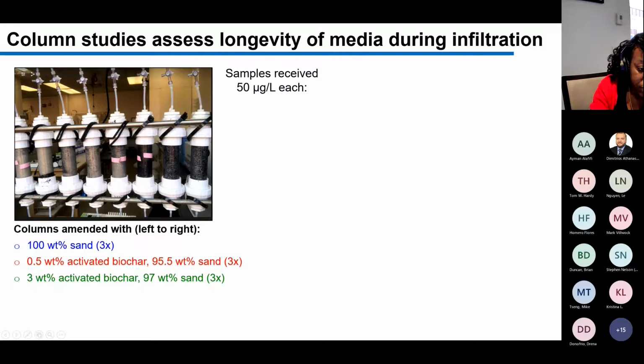And then from left to right here, we have triplicate columns of either sand only, and then sand dosed with different weight percentages of the activated biochar. So either a 0.5 weight percent amendment of the biochar or a 3 weight percent biochar amendment. And the idea here is that in a typical rain garden, sand is very commonly used. And if you add too much biochar, you could have a lot of adverse impacts, such as clogging, for example. That's been reported in some systems investigating applications of biochar during infiltration processes. So we just wanted to dose the sand with a bit of the biochar to increase contaminant removal, but also maintain certain hydrologic flow patterns in a typical rain garden scenario.